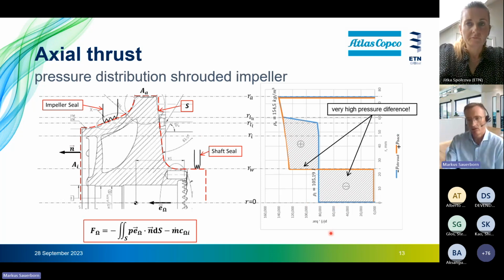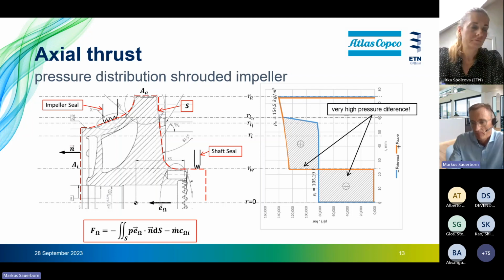We can observe that there's a huge pressure difference between the impeller shroud and backside, and this might lead to excessive axial thrust depending on the position of the impeller seal and the shaft seal radius. Last, the second term in the equation on the right describes the thrust component from momentum change as the flow changes direction from the axial to the radial direction. Due to the high density of the CO2, also this component contributes a significant share of the total thrust when compared to other applications. In our case, however, the overall axial thrust compensation is reached by balancing expander and compressor impeller on the same pinion in back-to-back arrangement.